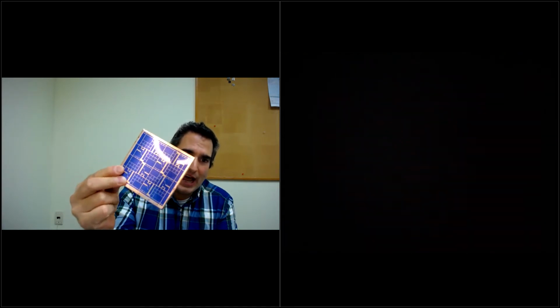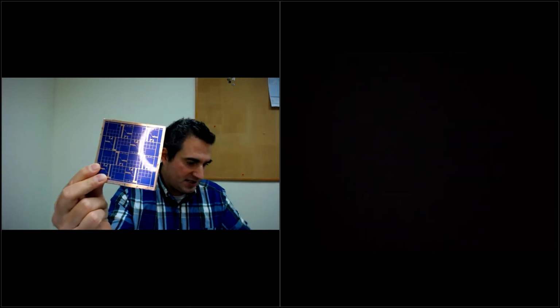So what we then do is we do the photolithography, where we take dry film photoresist and we laminate this DBC blank structure that we've built. And then we laminate it, right? Pattern, develop, expose, until you have your pre-etch DBC structure, right? So we know what we're going to etch. What looks like copper still will etch away. What is blue will remain. It's a subtractive process.